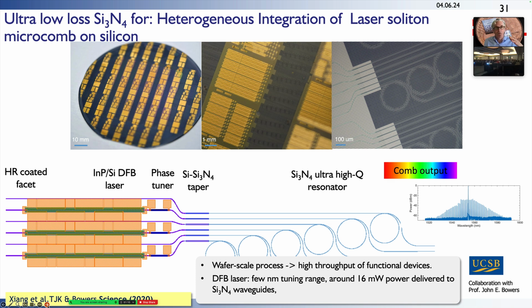We can even go one step further, and there's a collaboration with John Bowers' group where we combined the DFB laser directly with heterogeneous integration on the silicon nitride photonic circuit. What is interesting about this result is it shows the immense potential that wafer scale processing has, because here on this 100 millimeter wafer, there are more than 3,000 chip scale frequency combs being manufactured, which is a very significant number compared to, say, the fiber combs that are being employed today. So it shows that this technology really has potential for being used in applications.